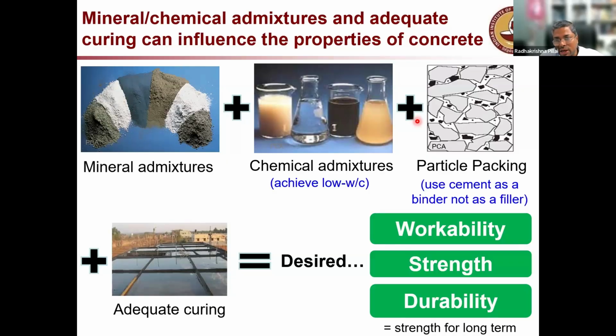Now people will say when you minimize the amount of cement, the concrete will not flow properly. What you do is you use chemical admixtures to make the concrete flow. Superplasticizers is one material which is widely used. Okay. So this is the idea. You have a minimal amount of cement in the concrete, and to make the concrete flow, you use chemical admixtures. And to enhance the property in the cement itself, if you can include more materials like fly ash, slag, etc., then you will get a very, very good quality concrete.